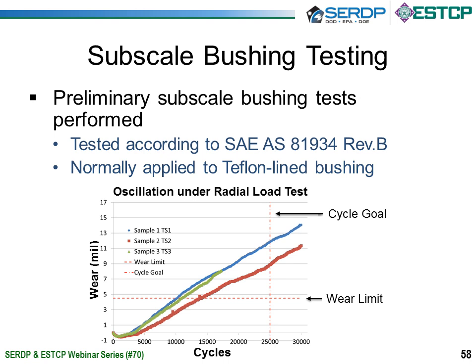In terms of the bushing testing, we did some initial subscale tests. They were tested according to an SAE spec 81934, which is a test for unflanged bushings. It's normally applied to a Teflon lined bushing, the Teflon really acts as the wear surface and the lubricating surface. So it was a very demanding test for these materials since they were run unlined. However, although the absence of the liner meant that the wear requirement wasn't met,